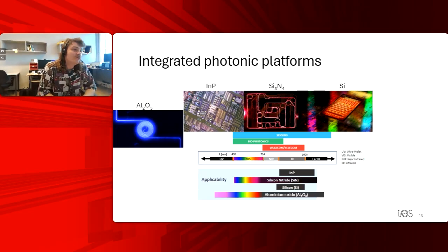It goes below the UV-blue operation of silicon nitride and even further into the infrared than all of these materials shown here, up to 5 microns of operation. And on the left there, you can see a picture of an aluminum oxide waveguide that I took in the lab, transmitting at 369 nanometers wavelength. So very, very small, below that 400 nanometer cutoff of silicon nitride.